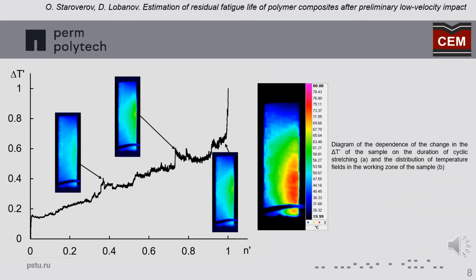The complex use of methods of infrared thermography and acoustic emission was applied. The combined use of these methods allows obtaining additional experimental data characterizing the mechanical behavior of the composite during the cycling test, the appearance and development of defective structure.